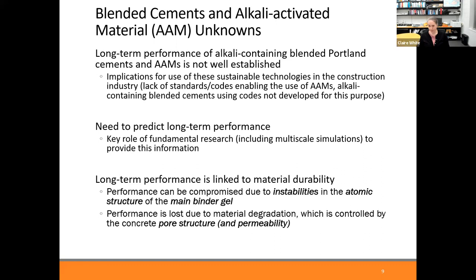And the long-term performance is linked to the durability of the material, how resistant it is to degradation. And this can be caused by instabilities in the gel itself. So understanding kinetics and thermodynamics is important. And also the pore structure of this material is very important because there are aggressive chemicals that get into concrete and degrade it. It's kind of funny, not everyone knows this, but carbon dioxide actually degrades concrete.